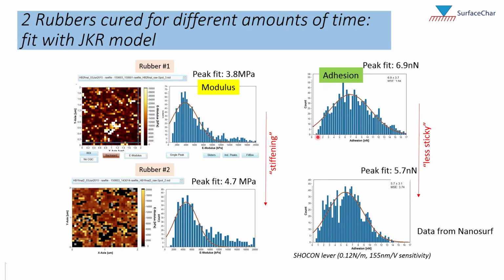Here is another example where I had two rubber samples and they had been cured for different amounts of time. Rubber 2 was cured longer than rubber 1. What I did was collect a force map on these two rubbers and measure the modulus and adhesion as a function of this curing time. And I could see that the second rubber was stiffer. It came in with a modulus of 4.7 megapascals relative to the first rubber at 3.8 megapascals.